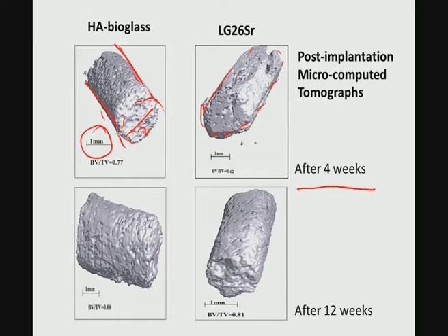So, the questions are whether the implant can retain its shape at different time points post implantation, and if the shape is not retained, whether there is any shape distortion or any sign of degradation of the implant in vivo. If the implant changes its size and shape, that will essentially indicate degradation of the material in vivo.